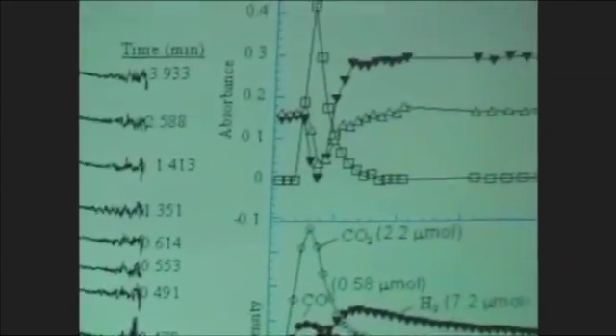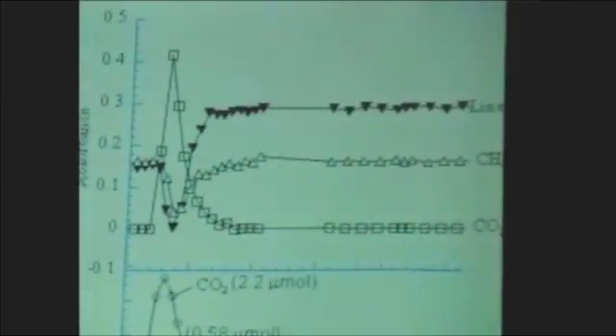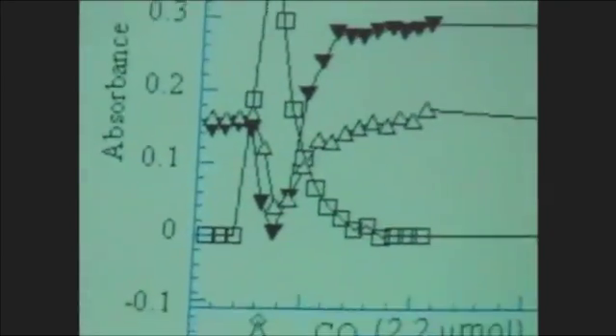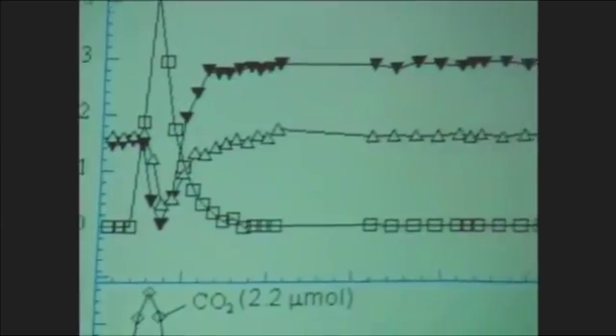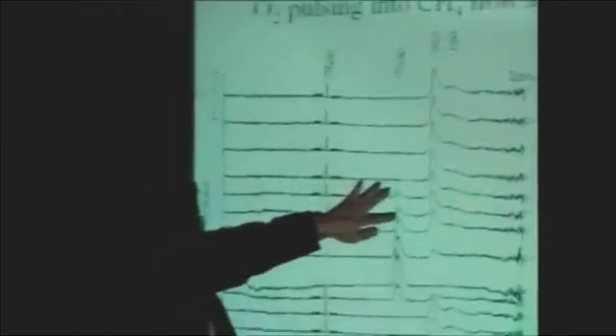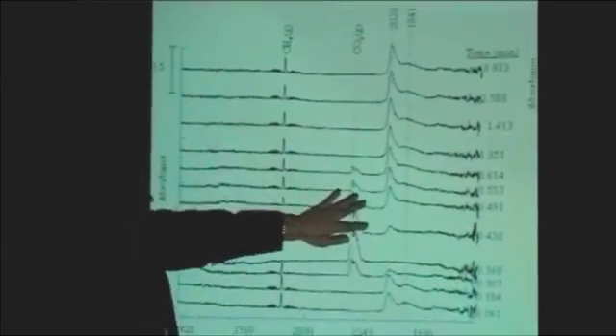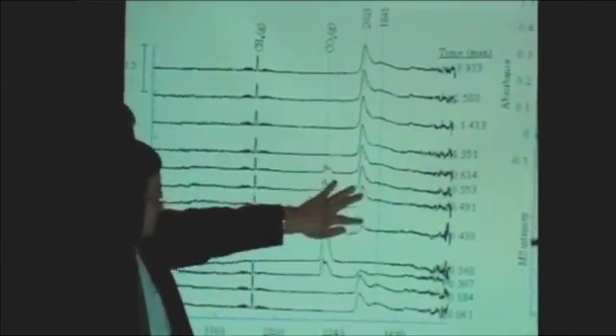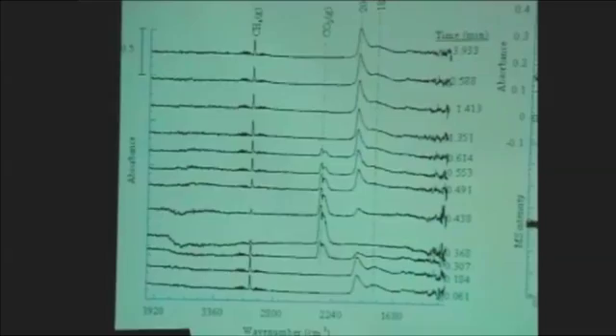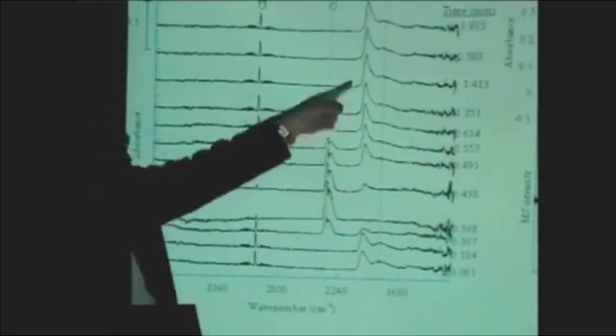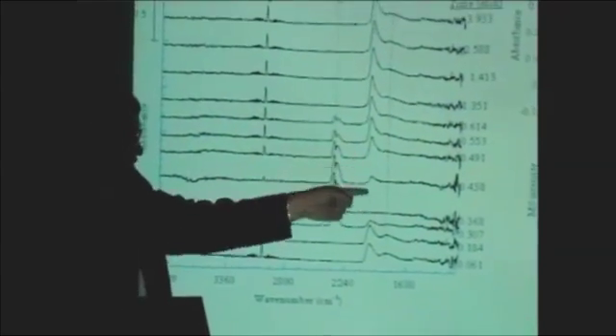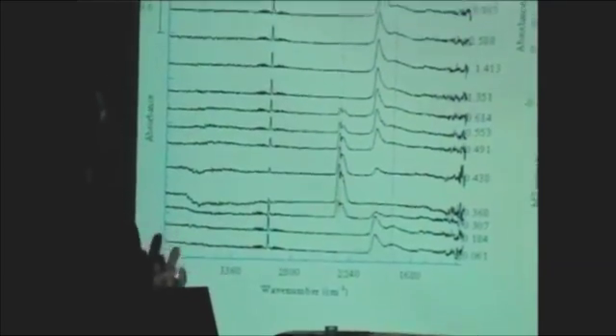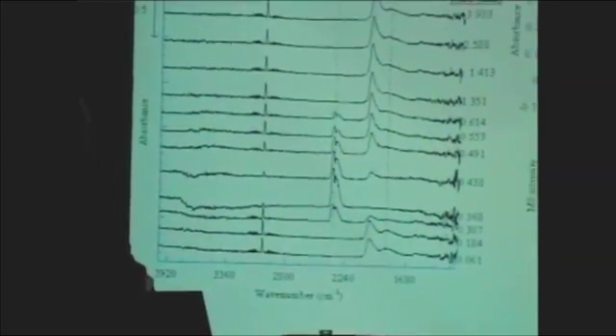In the partial oxidation reaction, certainly CO is adsorbed on the catalyst surface, but the CO is forming from the reaction of carbon and oxygen. And this step apparently is a much more rapid process. As the oxygen is coming in, we see the immediate formation of CO here. And in the reforming reaction, CO is being formed, but if we put oxygen in, the oxygen will immediately react with CO. So there is a different way the CO was produced and consumed.